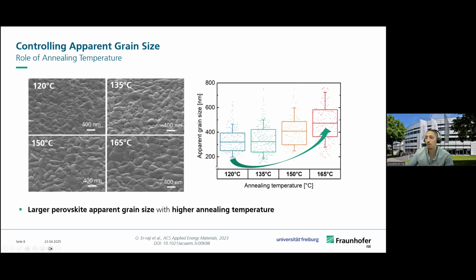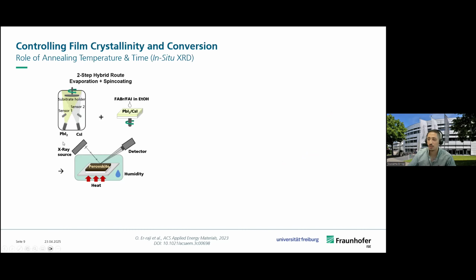Now, the annealing temperature in general, and also the annealing strategy, plays really a big role on the dynamics of the perovskite crystallization. And to get a bit more insight into how to control it, we carried out an in situ XRD study. So in the first step, we evaporated the scaffold, then we infiltrated the organics in the second step, and then we directly took our sample and went to an XRD machine where we placed our sample, closed the chamber, set a certain humidity, and then varied the annealing temperature and saw how the phases change and evolve during the crystallization.